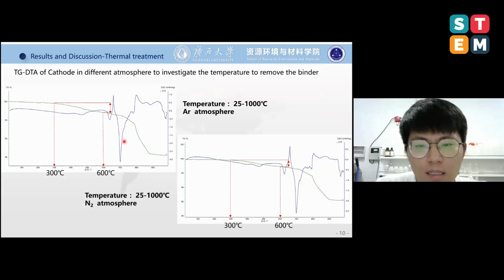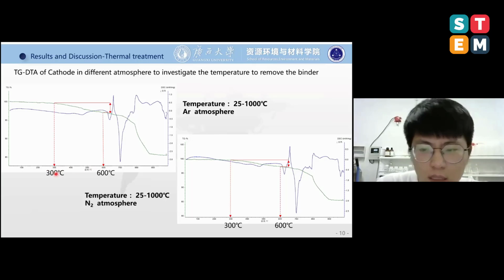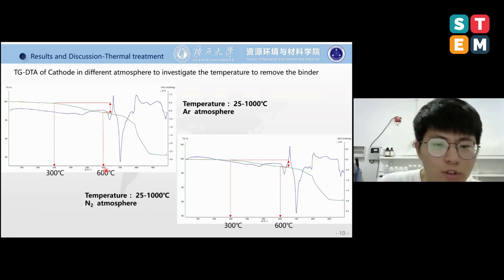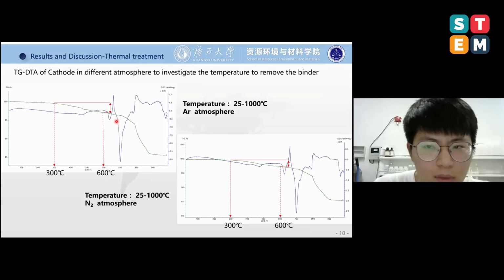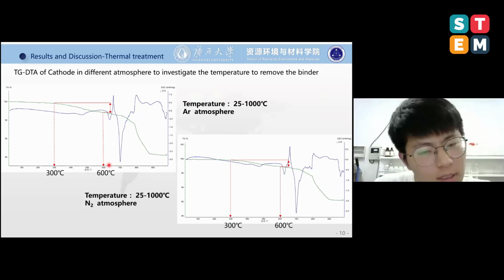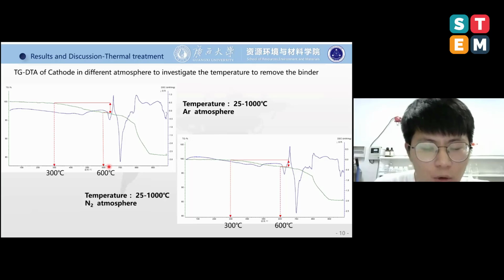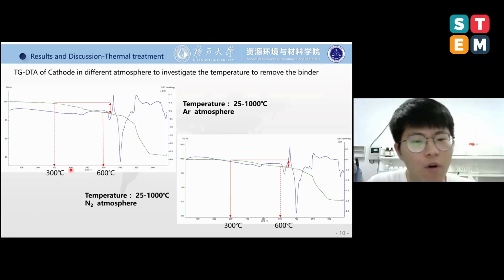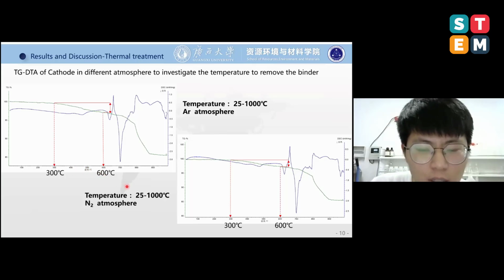And we can see these two pictures. There is not a large difference between them. And we can know from 300 degrees to 600 degrees, there is a weight loss. And when the temperature is increased over 600 degrees, the DSC has some peaks and something happened. As we all know, the aluminum melting point is about 660 degrees. So in the experiment, we choose 3 temperature points, 400 degrees, 500 degrees, 600 degrees.